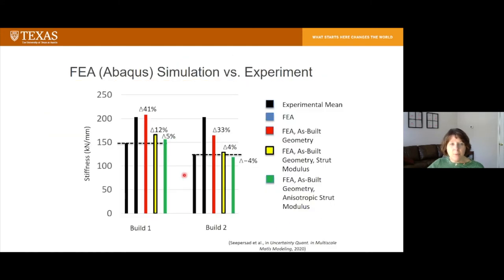So when we incorporated that information into our finite element analysis models of our lattice structures, all of a sudden our errors went down to less than 5%. So we really need to know what's going on with these struts and take that into account to get an accurate prediction of the performance of these specimens.